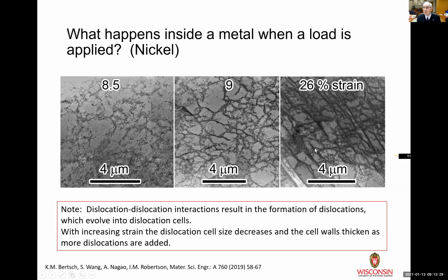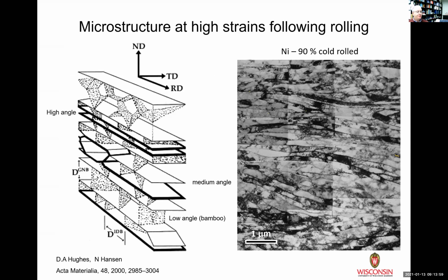Of course, ultimately what will happen is the material will get to a certain cell size and then it will stop, right? The material can no longer accommodate the plastic strain through dislocation cells and the motion of these dislocations between the cell walls. Other things will have to start happening. What starts happening is that you get rotations between the individual cells. And if we look further, this is what you get. This is what happens when you cold roll to 90%.